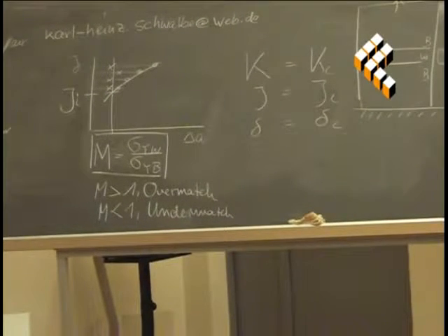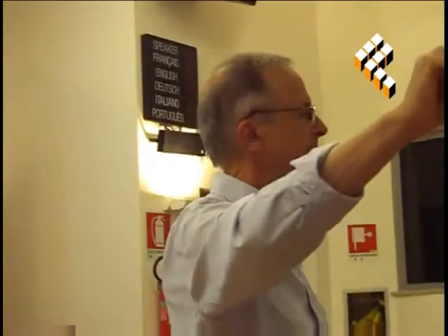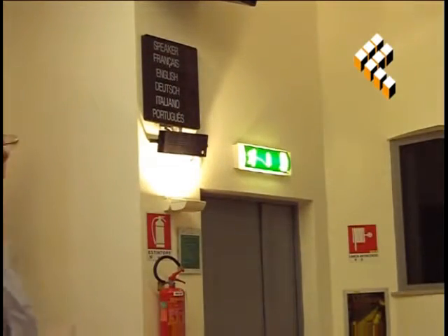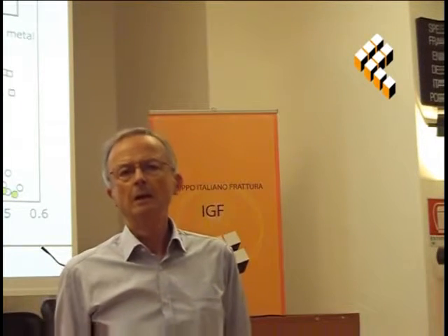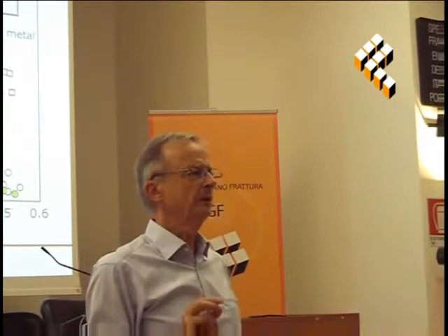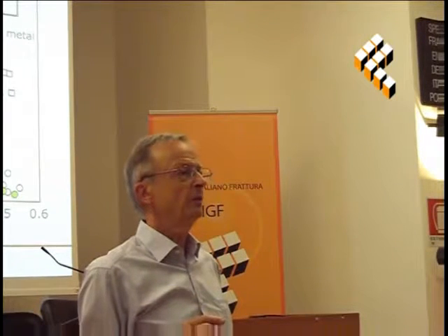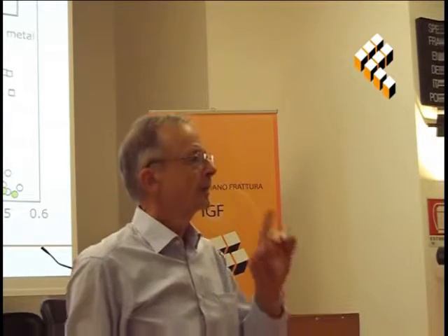Because apart from fracture mechanics, if failure would occur, then it shouldn't occur in the weld metal, but somewhere else in the base material. Because everybody has known for a long time that the weld metal is usually, with its properties, worse than the base plate. So failure should not occur in the weld metal. That's why people try to achieve overmatch, which can be easily said.